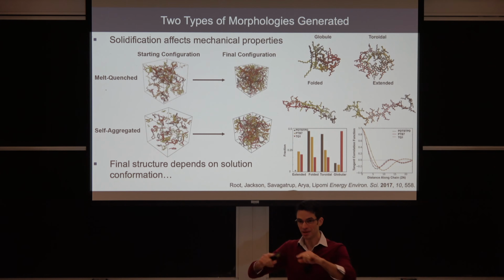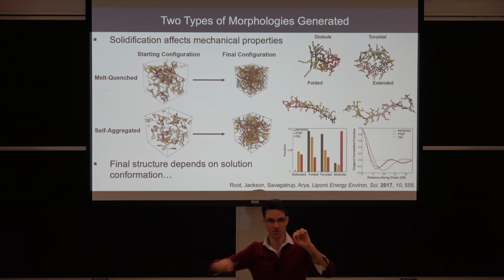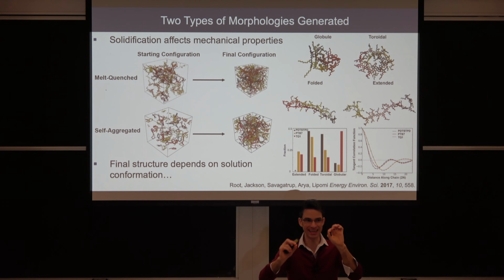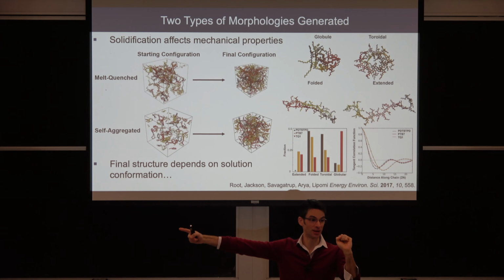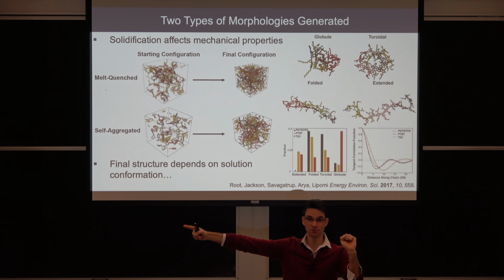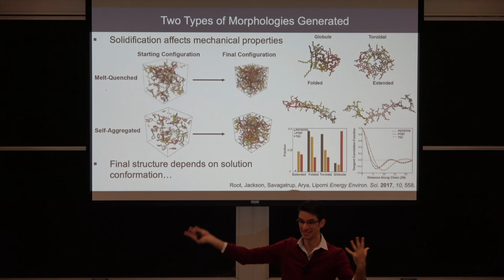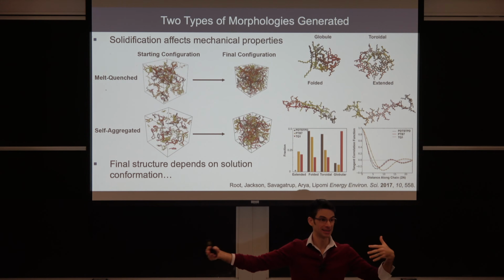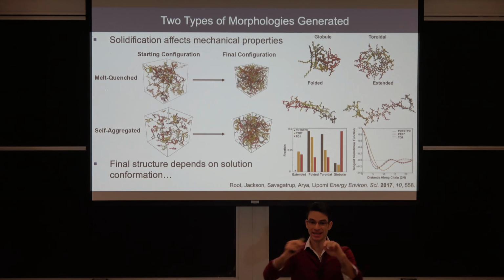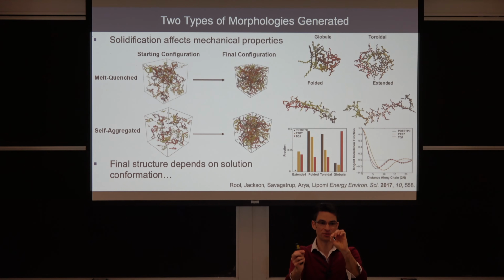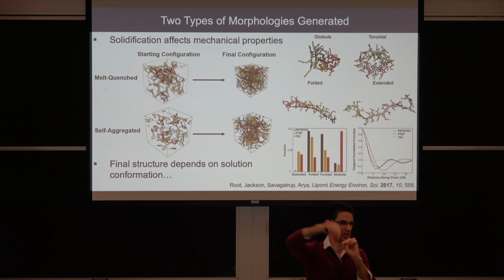Okay, so imagine that you have this polymer chain, and you can draw tangent unit vectors along each monomer in the chain. So the tangent correlation function is the dot product of the tangent vectors between some reference monomer and some monomer farther on down the line. Now, you would expect for a completely disordered mess of a polymer chain, like a random coil, like a globule, that you would have some correlation for the first few monomers, and then it would be pointed in whichever way.